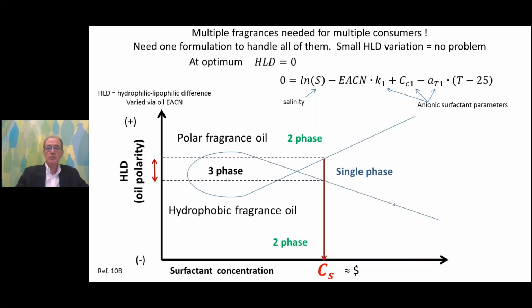When we have a good match between our surfactant system or our single surfactant and our fragrance oil, the HLD is 0. The HLD equation tells us that's an optimum point for solubilizing that particular oil with a particular EACN. Well, if we have a range of fragrances that show a very small range in EACN, then the HLD range is going to be relatively small, and we should be able to achieve a single phase system with a single surfactant formulation at some concentration, and concentration of surfactant translates to dollars, of course. So when we have a narrow range of HLD to cover, we don't seem to have a big problem.